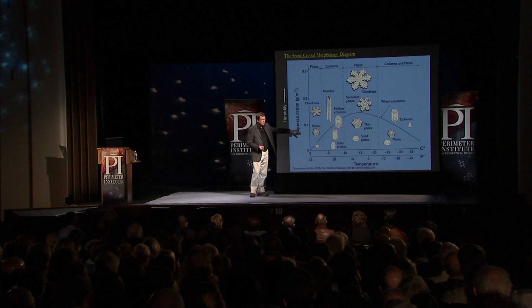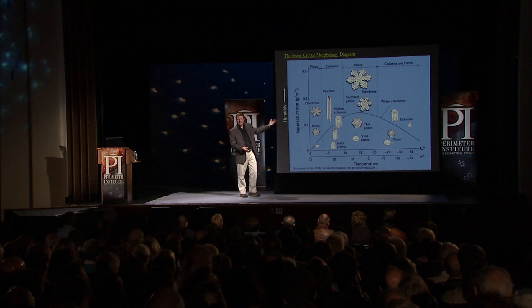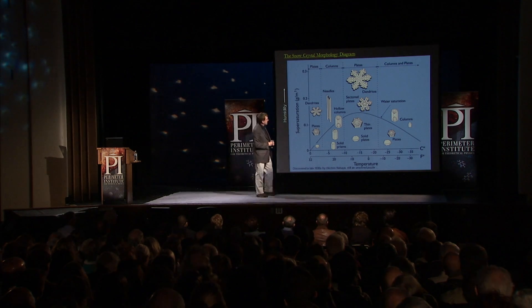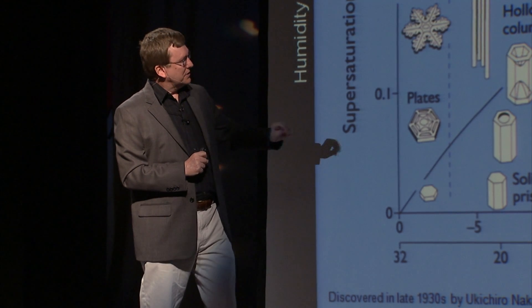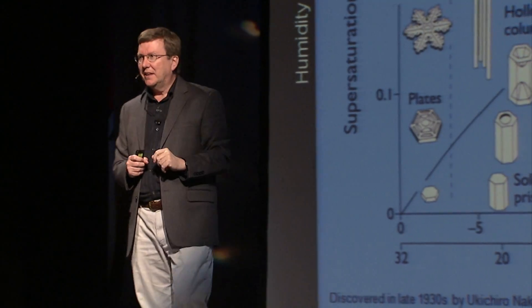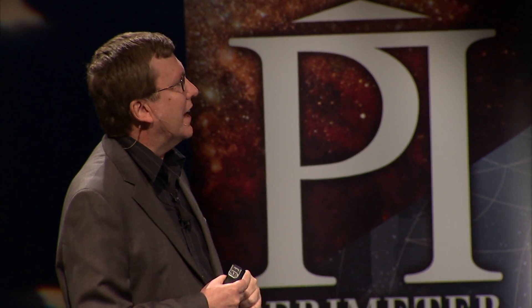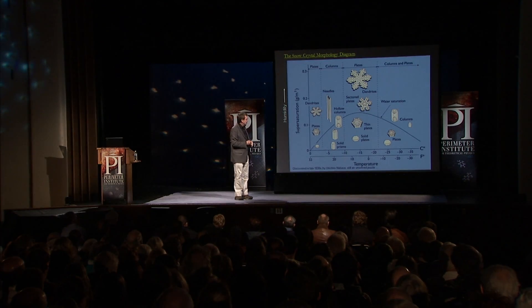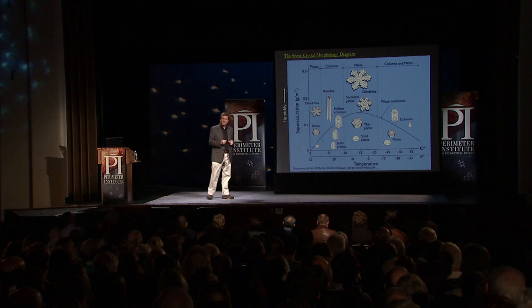Here are some crystals grown at minus 2 Celsius — mostly little plate-like hexagons, about 50 microns, roughly the diameter of a human hair. At minus 5, instead of plates we have columns — long, skinny, six-sided, like wooden pencils. At minus 15, we get plates again, but big thin ones. By doing the experiment over and over with different conditions we get the snow crystal morphology diagram: temperature on one axis, supersaturation on the other. At low supersaturation you get simple prisms; at higher supersaturation, more complicated shapes. And they switch from plates to columns to plates to columns as a function of temperature.